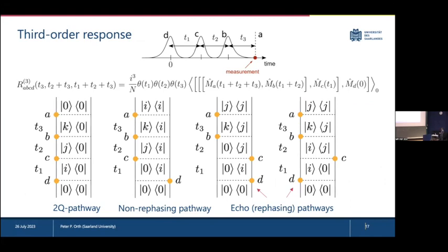And so, for example, you could imagine, let's say you have 2 excitons, but they interact. The phase acquired during this time T2 is not just the sum of the phases you acquire with single excitons. So you can get some information about interactions of quasiparticles. There are also echo pathways where phases that you acquire during one time evolution will be exactly canceled during another time evolution, and that can be used to look through inhomogeneous broadening and learn something about the intrinsic lifetime of particles.